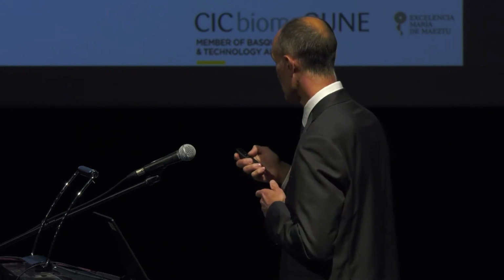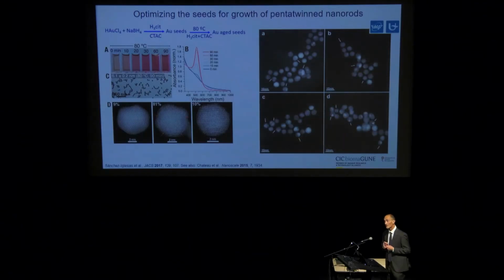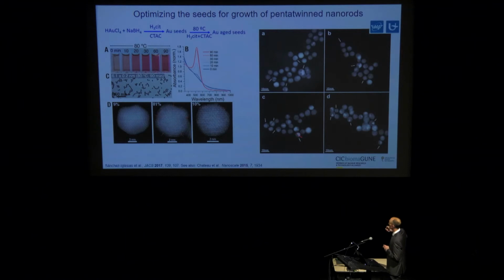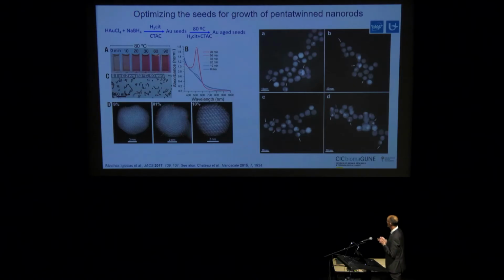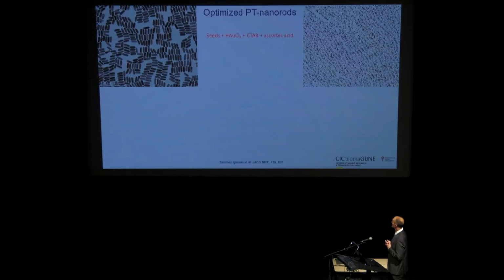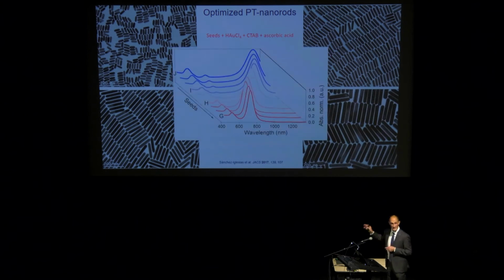And they were able to do statistical analysis of the population of pentatwin seeds and corroborate that this increase in particle size, which is also reflected in a more intense plasmon resonance, leads to many more pentatwin particles that you can then use as seeds. And this is again against previous works, because now these seeds are about 6 nanometers in diameter, which have always been thought to be too large to act as seeds for the growth of nanorods. However, if we now use these ripened seeds, we are able to obtain pentatwin rods that always look like this.